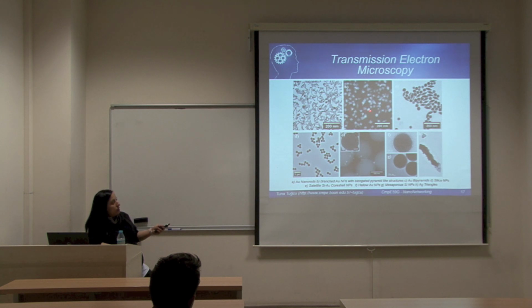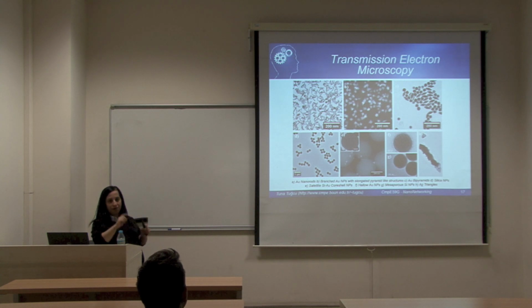Here is again gold. We have star structures and bipyramidal structures. You see they're quite pointy, these nanoparticles. We use these nanoparticles for catalytic surfaces because, since they're quite pointy, you have a lot of active surface that you can play with. Again, here we have a gold-silver composition, two types of nanoparticles, and what we call a bipyramidal structure, because it's like a pyramid but a double pyramid. Each different shape can have different applications. Here we have some silica beads, if I was not wrong.